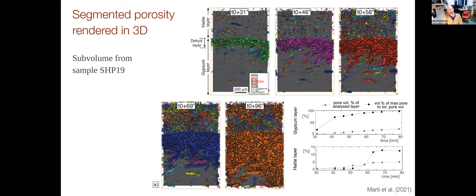Here we still have these isolated pores in the halite, growing porosity here. And then there's this moment when suddenly porosity really increases. And you can see that down here in these curves where the green curve is actually showing porosity increase. And the black curve is more important here. That is how much of the total porosity in that layer is accommodated by the largest interconnected pore, right? Which is essentially here, that one. But then here, we have through-going porosity all the way, right?